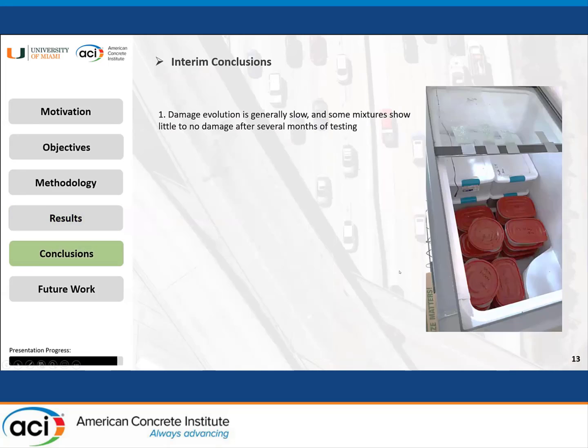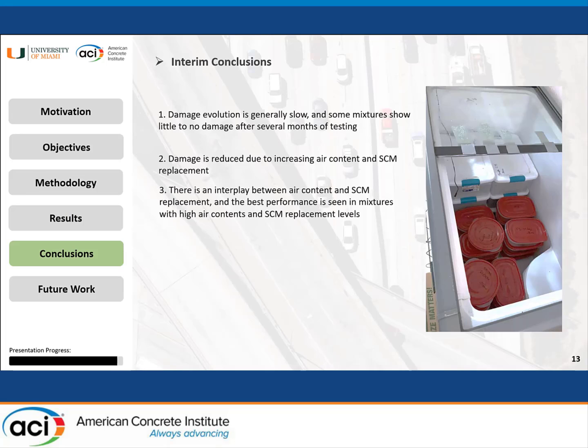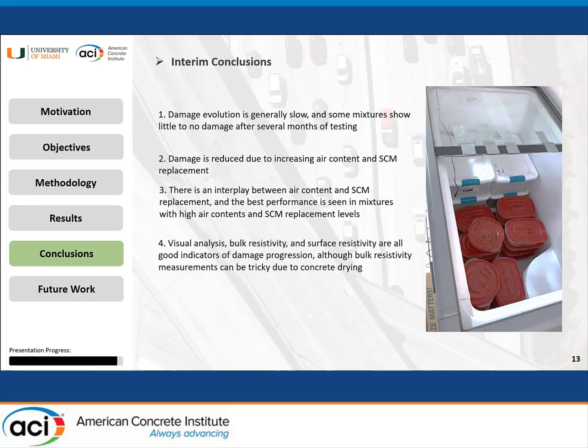So let's get to some interim conclusions based on the results that we have so far, as we're still continuing this experiment. The damage evolution is generally slow, and some mixtures show little to no damage after being exposed to several months of testing. The damage is reduced due to increasing air content as well as SCM replacement. There is an interplay for sure between air content and SCM replacement, and that's why the best performance is seen in the mixtures with high air contents and SCM replacement levels.